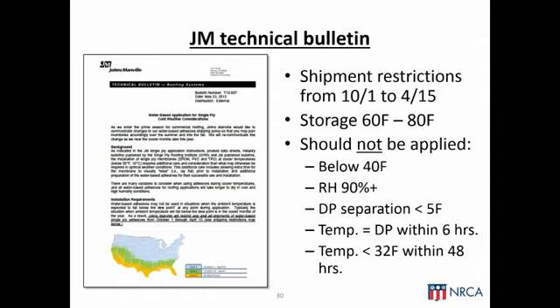For example, temperatures under 40 degrees, when the relative humidity is high, when there's not an adequate dew point temperature or dew point separation, and when the temperature and the dew point will converge upon themselves within 6 hours of installation. And also if there's going to be a temperature drop below freezing within 48 hours after installation. In other words, temperature and humidity become key factors in when a water-based bonding adhesive should be used and when it should not.